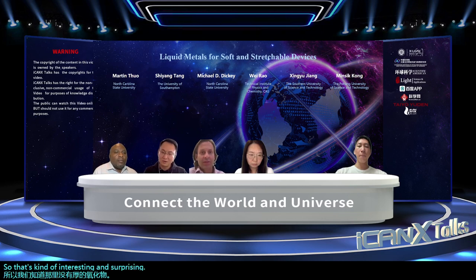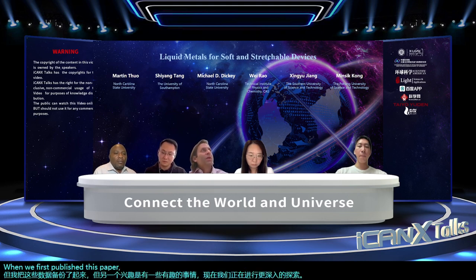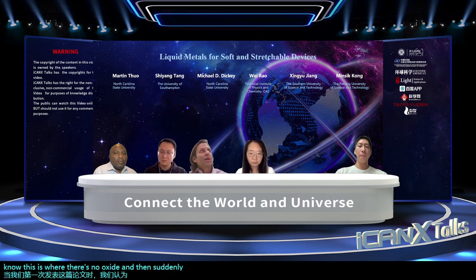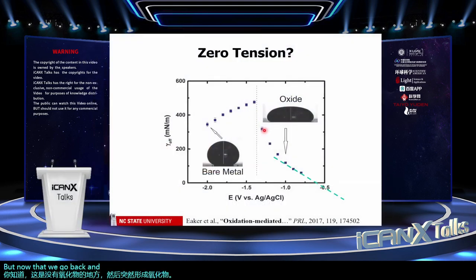The other thing that's interesting is, I think I should be able to share my screen here, but I pulled this data back up. There are a few interesting things now that we're taking a deeper dive. When we first published this paper, we thought that this is where there's no oxide and then suddenly the oxide forms. But now that we go back and do it very carefully, we find that there's actually one little oxidation peak. So there's something that forms on the surface, but the tension actually doesn't drop initially. It's only when we start breaking down the oxide that it will start lowering the tension. So actually, there might be a little bit of oxide here, and then boom, it starts to drop.